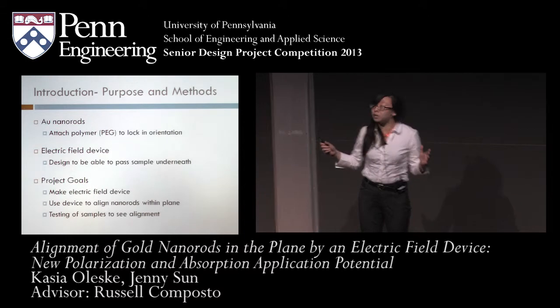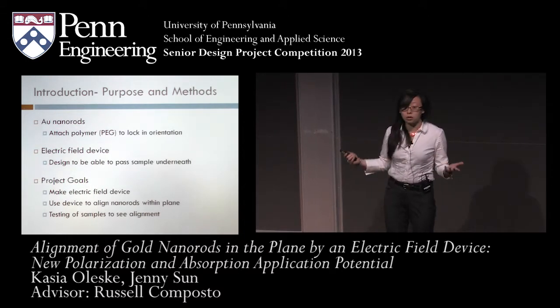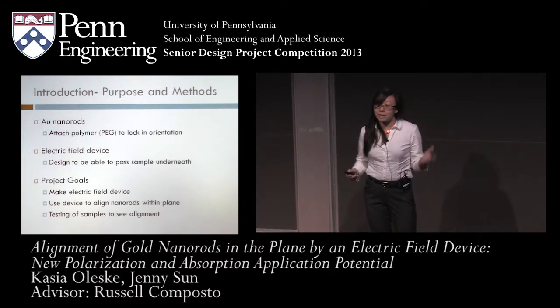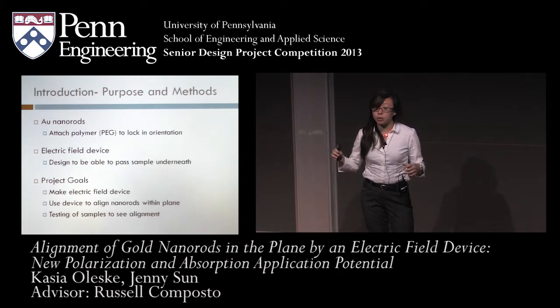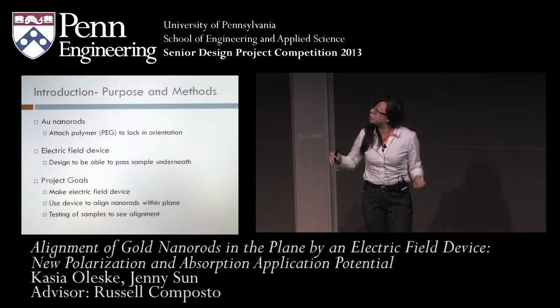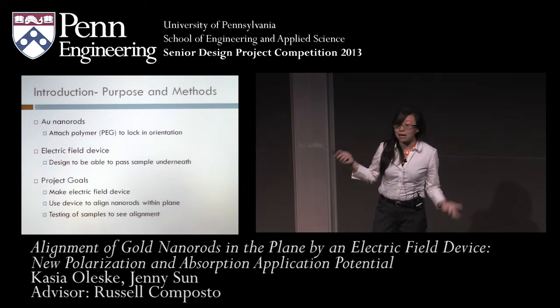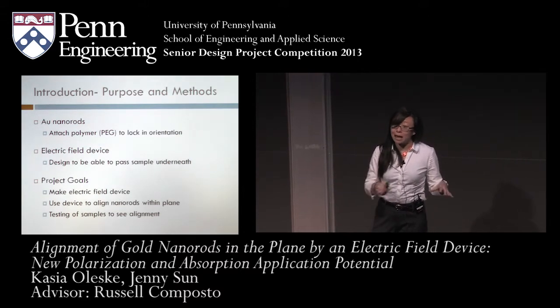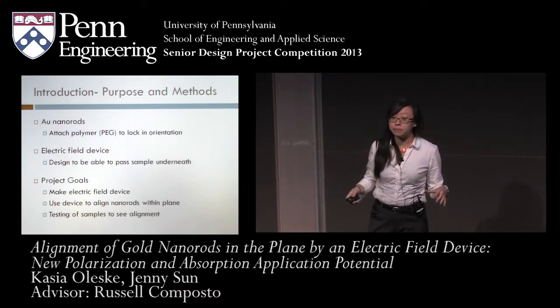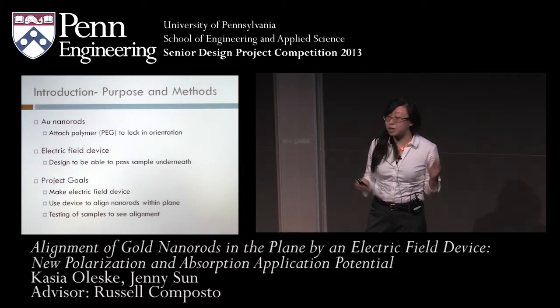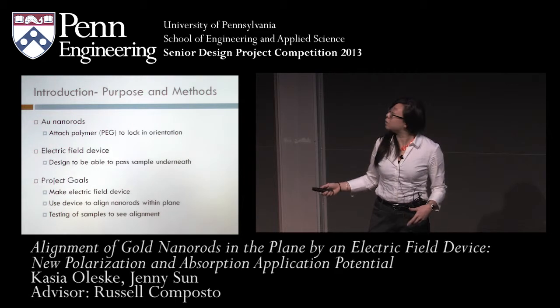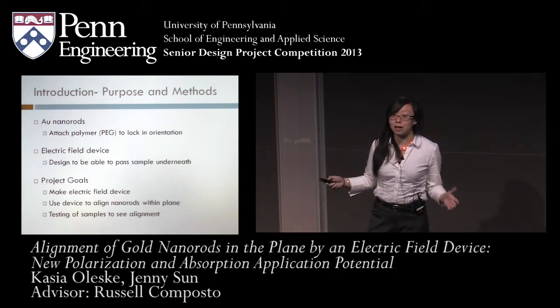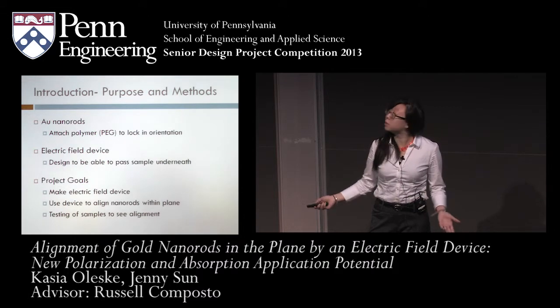So an introduction of what we did. First we used gold nanorods, to which we attached a polymer matrix in order to make them orientable and alignable. And then we had to design an electric field device in order to actually align these nanorods. We needed to be able to pass our samples underneath this device, underneath an electric field, in order to align them. And so the rest of our project was, after we built our device, to run our samples through it and then test to see alignment.